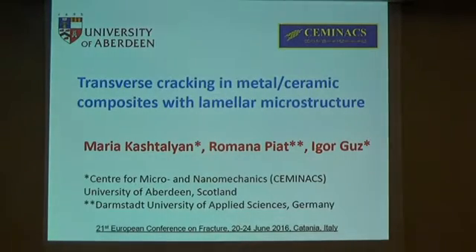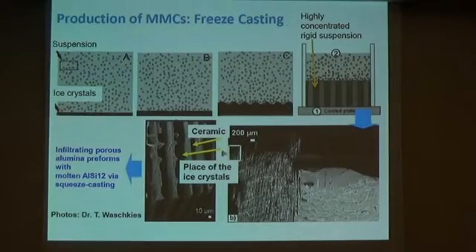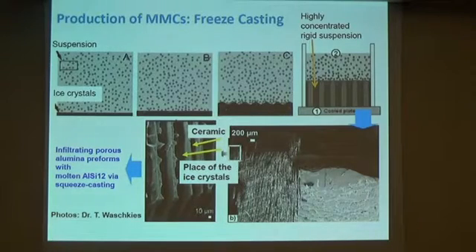So metal ceramic composites with lamellar microstructure are a novel class of metal ceramic composites which are produced using an innovative technique called ice templating or freeze casting. That technique involves taking ceramic suspension and freezing it. And as ice crystals grow, they push ceramic particles around, and layers of ceramic are formed, and a porous preform is produced when ice is sublimated and freeze-dried.